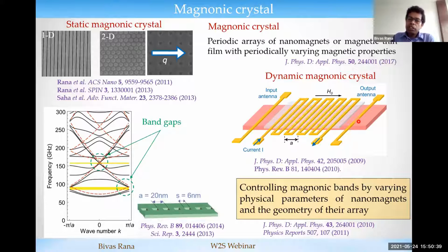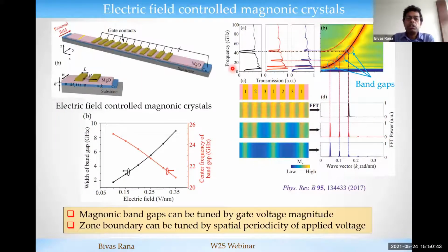But can we also create a magnonic crystal by using voltage controlled magnetic anisotropy? Yes, of course you can do that. That has been shown by Professor Hillebrands' group. Basically, you periodically arrange the top gate electrode and apply a gate voltage to tune the perpendicular anisotropy in the system. Then if you look at the spin wave dispersion relation, you can see a Brillouin zone boundary, given by the inverse of the periodicity of the gate electrodes. At that zone boundary, the spin wave cannot propagate along this waveguide. Interestingly, the width of this band gap can be tuned by changing the value of the gate voltage.